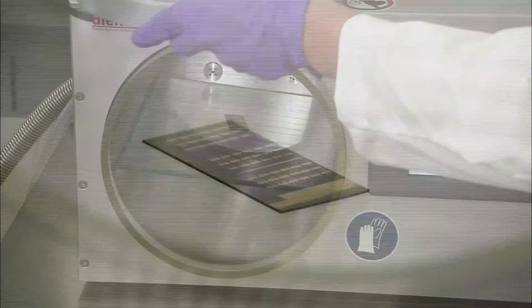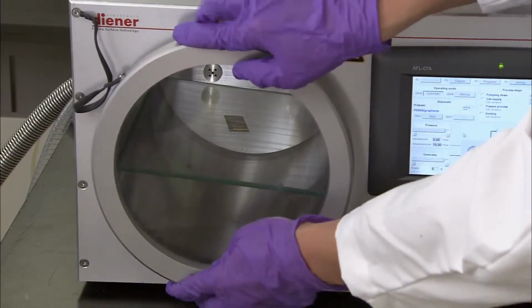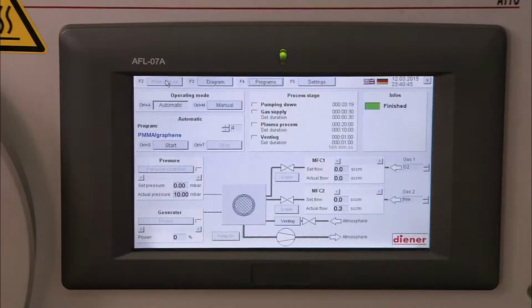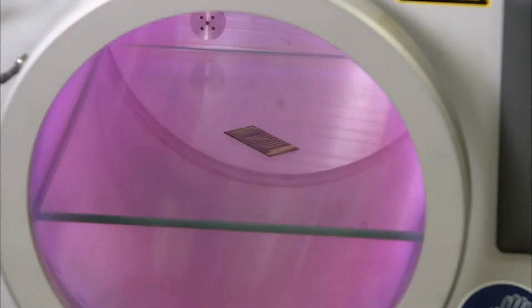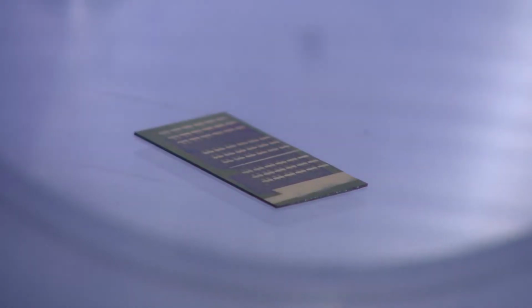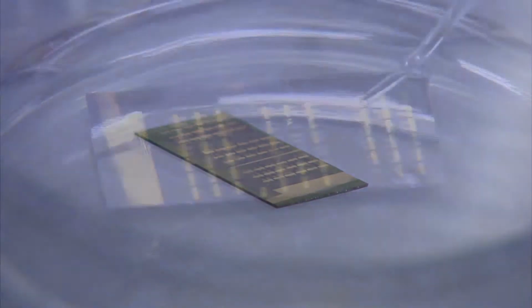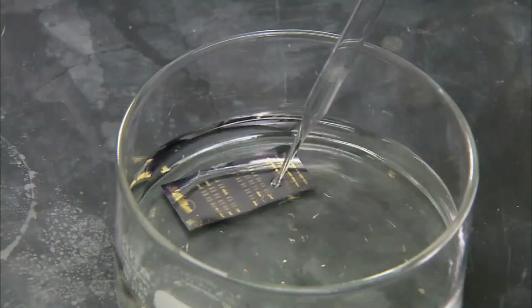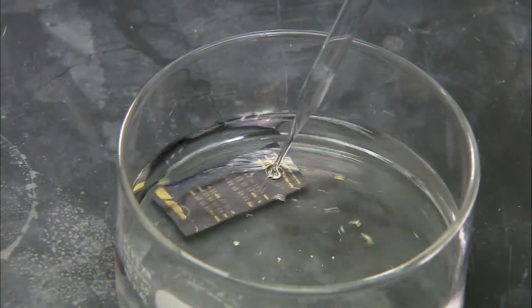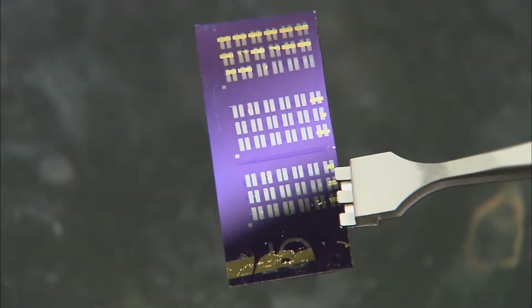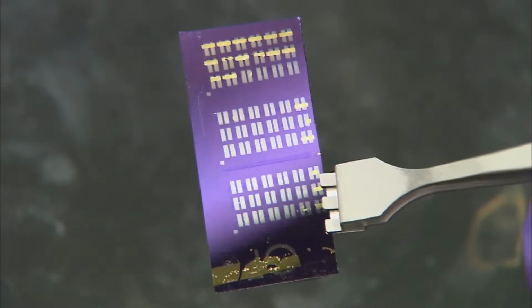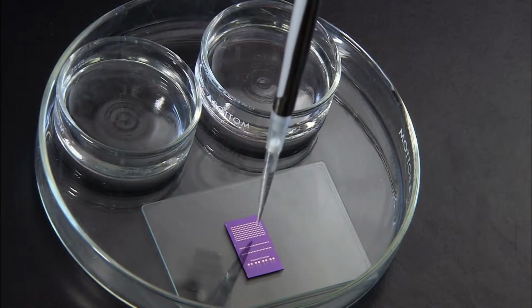The stencils are then removed from the chips, revealing gold horizontal runners between the contacts. The chips are then transferred to a plasma etcher. Plasma gas floods the chamber and strips off all the graphene that isn't protected by gold. Only the gold contacts and the gold-covered graphene runners remain on the chip. Solvent is used to dissolve the plastic backing. It takes the protective gold with it, leaving only the graphene behind. We now have a completed graphene sensor chip.